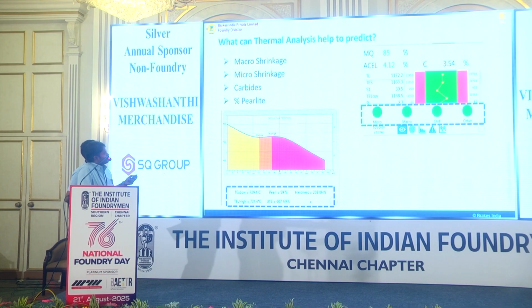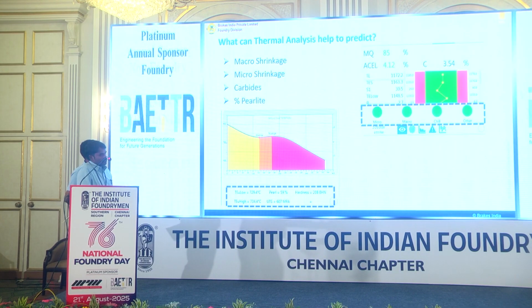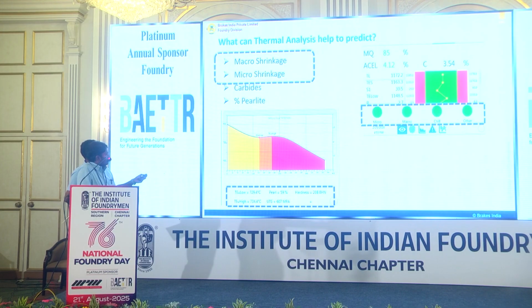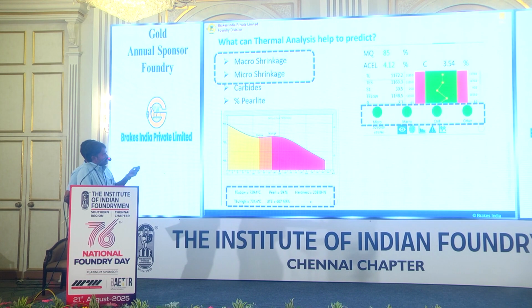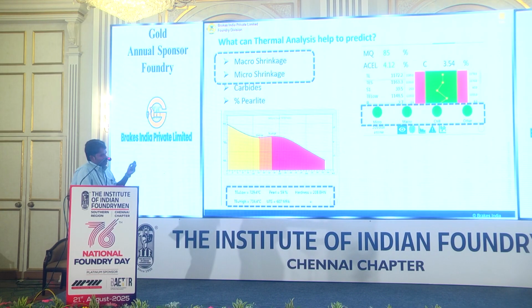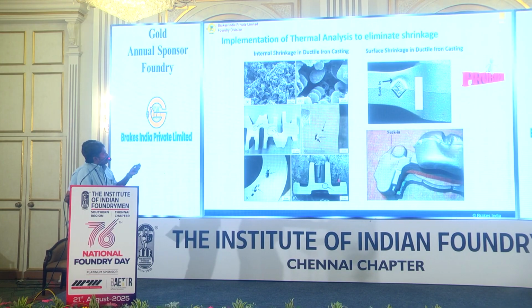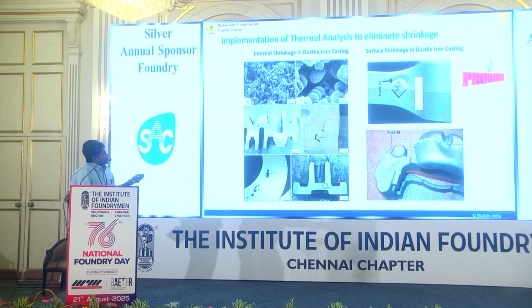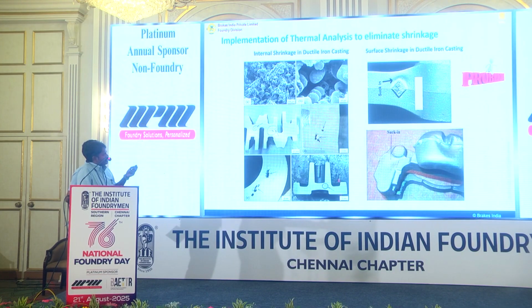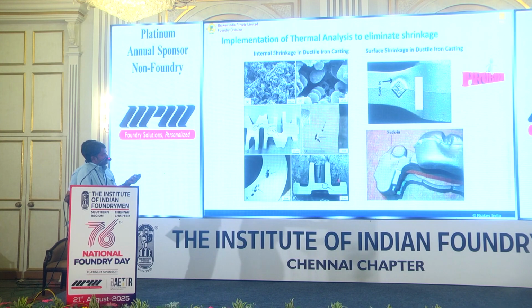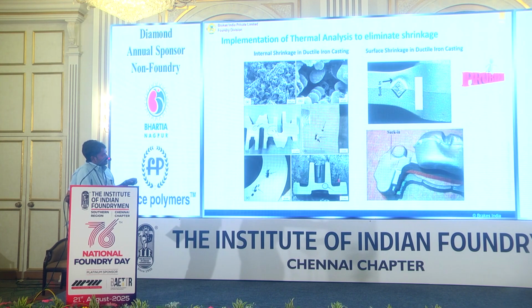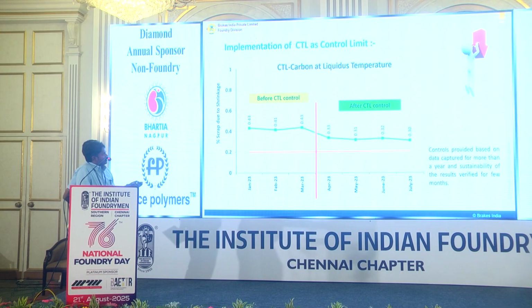So we can predict this. We can predict micro shrinkage, carbides, as well as mechanical properties through the thermal analysis system. This is one example of how we can control the mechanical properties also in the thermal analysis system. This topic mainly focused on shrinkage, especially macro and micro shrinkage. This is a pictorial representation of micro shrinkage as well as surface shrinkage or macro shrinkage. Micro shrinkage is present in the inner portion of the castings in a spongy-like structure, and surface and macro shrinkage is present on the surface as well as inside the casting in big voids.